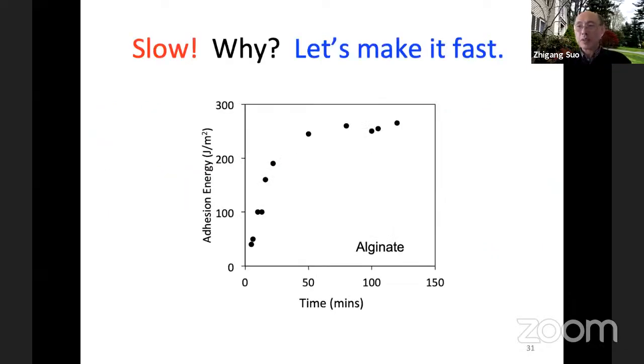Now there's a problem. We made a further discovery: it's very slow, very slow. So adhesion energy, we measure by a peel test, as a function of time after you form that adhesion. To reach 100, 200, 300 adhesion energy, you need 50 minutes. That's bad. If you talk to surgeons about 50 minutes, this cannot be used in surgery, right? Too slow. So the first question is why is it so slow, and can we make it fast?